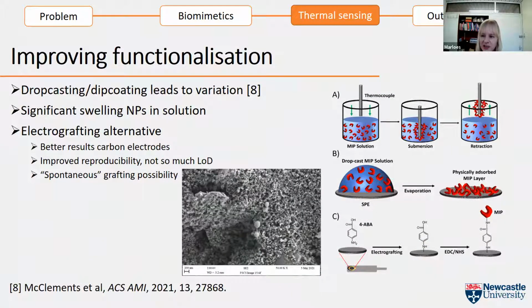And thinking of it, if you just drop cast or dip coat a material on it, it's not that interesting because it's not necessarily the most reproducible. So if you go to a company, they're not necessarily happy with that. So what we have done is that we've taken that material and we used a different approach, which is also quite fast, but it's based on electrografting. And then we can really reproducibly add a lot of nanoparticles with a very high surface coverage.